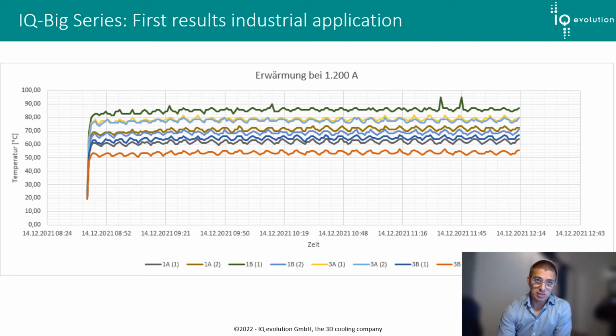What you see here is a 350 kilowatt test stand for an inductor from one of our customers. They have run it at 1000 and 1200 amps with a conventional cooler and our solution. For both evaluations, they have used silicon carbide devices in the same module, hence it's a very good apple-to-apple comparison. What you can see is that with the conventional cold plate, the temperature varies from roughly 50 to 95 degrees, and a lot of damping is required.